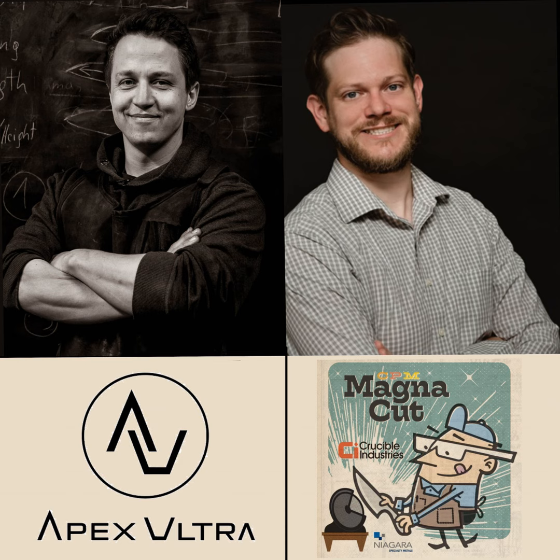It could be overheating in that case. Yeah, that's what I thought. Especially when you're laminating, you're always pushing the temperature up, right? So you're like, I could do 1150, it's gonna be fine. But if you go a little bit too high, then you can mess up the steel, and that could show up in dots. Curious to see what Larrin's theory is, but it's one of the most common mistakes. I get a lot of, what did I do wrong? I have cracks. What did I do wrong there? And usually it's overheating during forging, cooling too fast after forging, or basically not sealing the weld when forge welding.